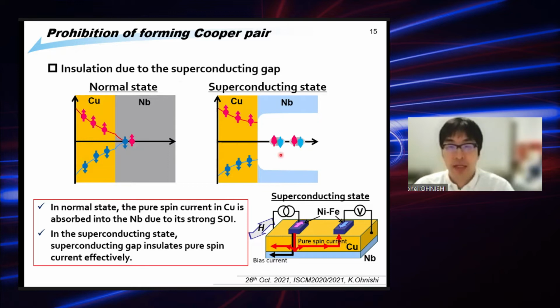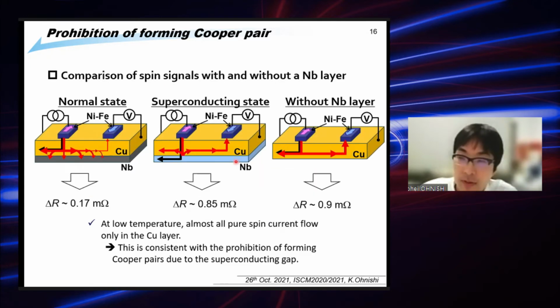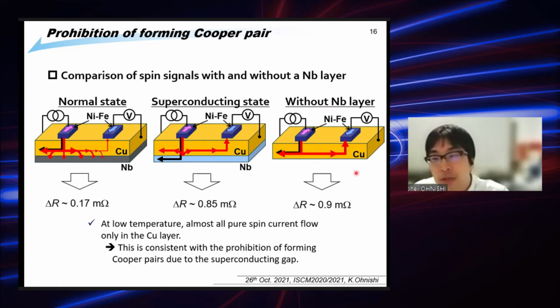This is a good explanation, based on the schematic shown in the introduction. To confirm this schematic explanation, we also fabricated a sample without the niobium layer like this. And as the result, in this structure we can observe a spin signal of 0.9 milliohm.